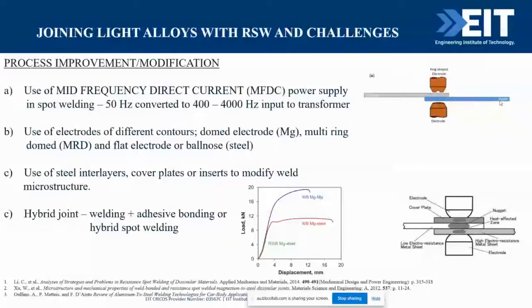Now this will create a heat balance. The problem with spot welding all along, even before this, is welding materials of different thicknesses. Creating a proper heat balance has always been a challenge, especially now with different materials. So by using different electrodes, different contours of electrodes, we can actually create the spot weld. That is something that's being looked into. Another common modification that is being researched, not really gone into practice yet, is the use of steel interlayers or inserts and so on. Now there may be an issue with this, because at the moment we are trying to reduce the weight. That means we are trying to go into lighter materials, my apologies, not lighter welds, lighter materials.